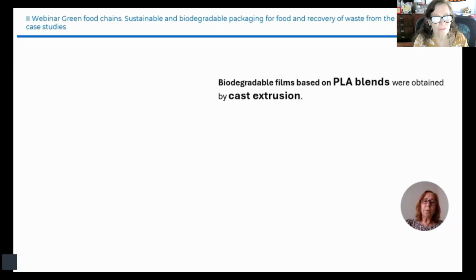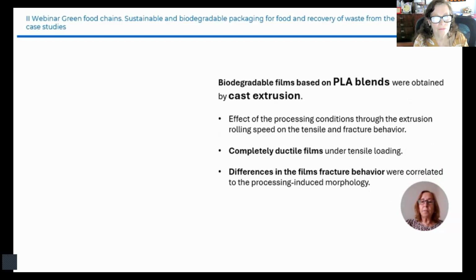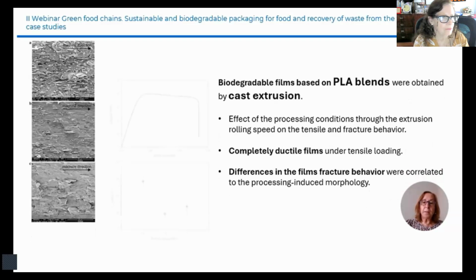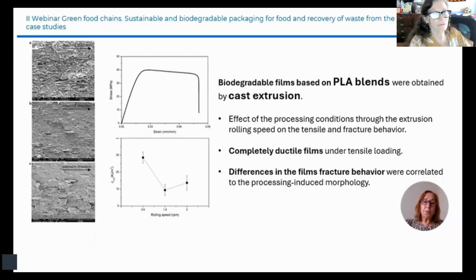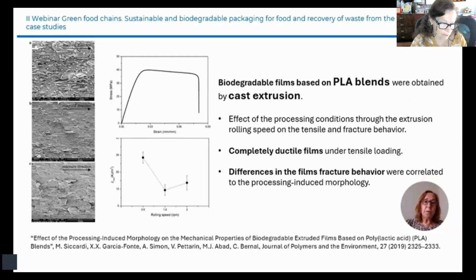In collaboration with the University of Coruña, Spain, we also developed biodegradable films based on PLA blends. These films were obtained by cast extrusion, and we analyzed the effect of the processing conditions on the tensile and fracture behavior through changes of the extrusion rolling speeds. The films were completely ductile under tensile loading, but we observed differences in the films' fracture behavior, which can be correlated with the processing-induced morphology. You can see on the left the scanning electron microscopy images from the different films obtained.